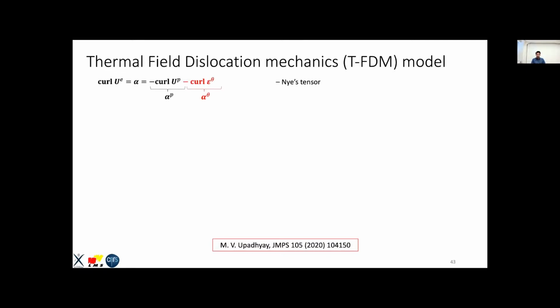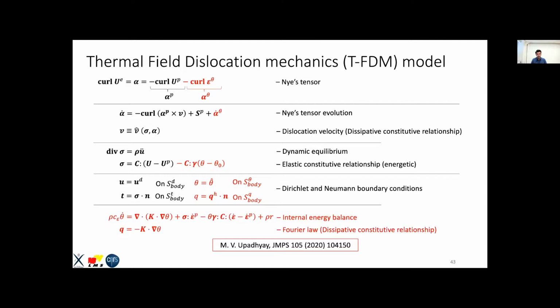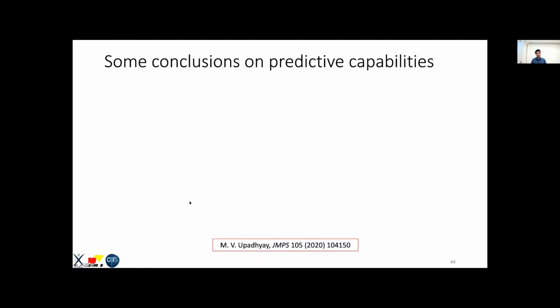When I combine this together in a strong coupling with heat conduction, this is the model that I get. All these red parts are the new additions to the model. You have the contribution of the thermal changes into the dislocation density and the evolution of the dislocation density field. And you have temperature changes that occur due to plastic distortion evolution and plastic strain evolution. Then these are the elastic laws and the dissipative law, the Fourier law of heat conduction, that you get out from energetic and dissipative analysis.